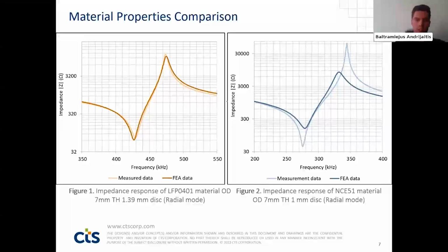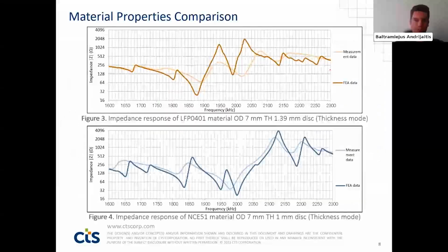And on the right here, we see lead-based material, and you can see the curves are a bit mismatching, because this wasn't tuned. The same comparison was done at higher frequencies. Here on both graphs, we can notice a mismatch of material damping and a mismatch of resonance frequencies, which indicates that our matrices of material could be tuned more. However, resonance frequencies do not differ by more than 4% here, here, here, and here. And we assume that the finite element models are valid for further development.